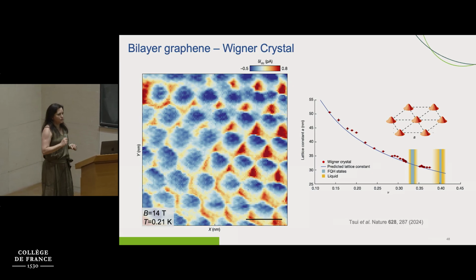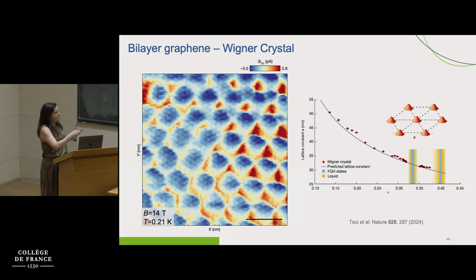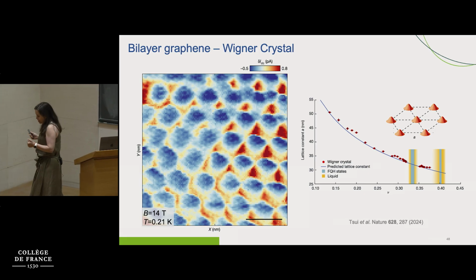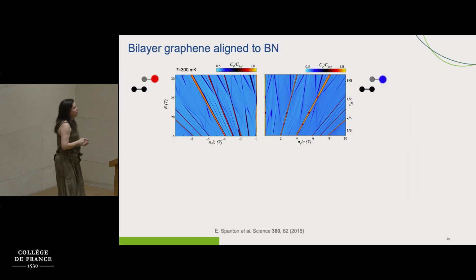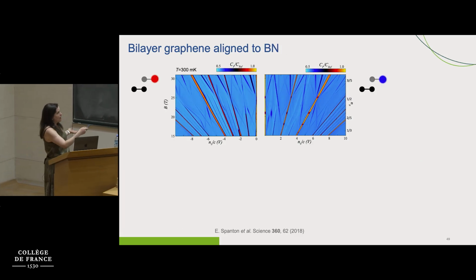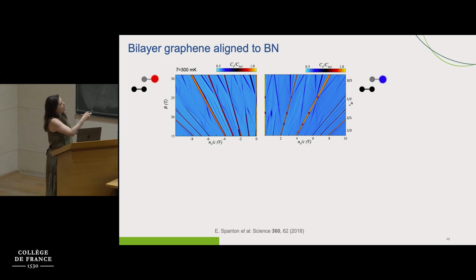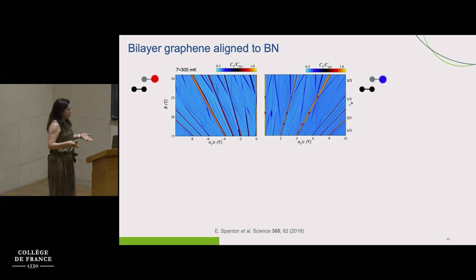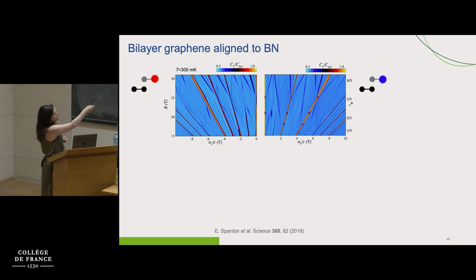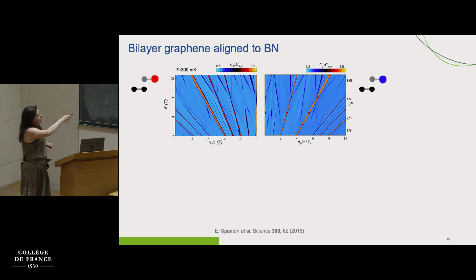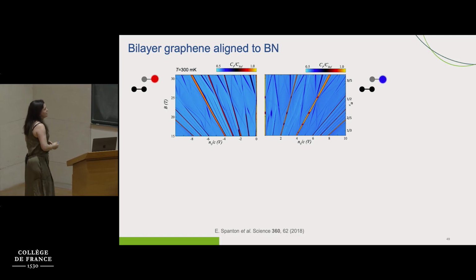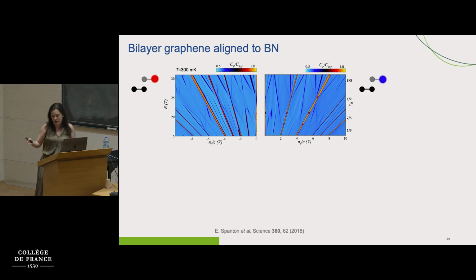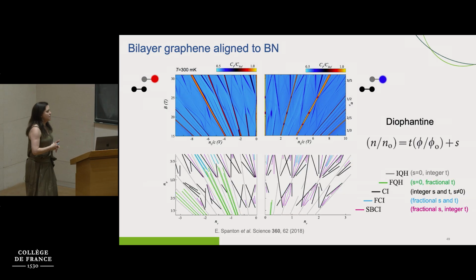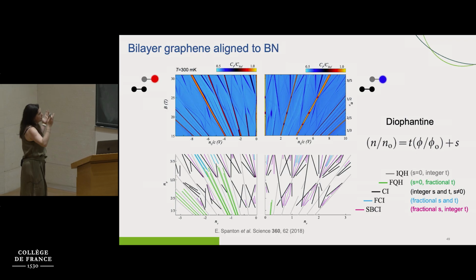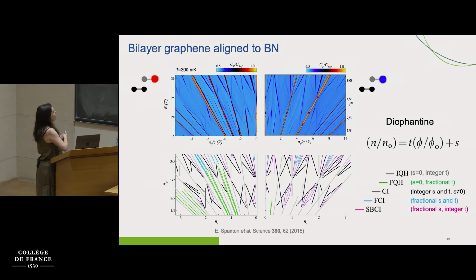So now, Hofstadter butterflies. No, we were at that because we already saw this before. Let's put a moiré on top of that. So if we look at the Hofstadter butterfly of a bilayer graphene, in particular at the very high flux, very high number of flux per Moiré superlattice, which means a high magnetic field, we are going to see just a full zoology of states. And these states separate or have their own topological significance. So what we are seeing here is what I think is an extremely beautiful map of all the topological states that we can have.